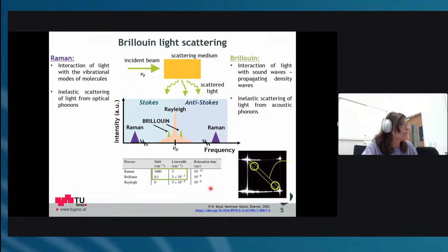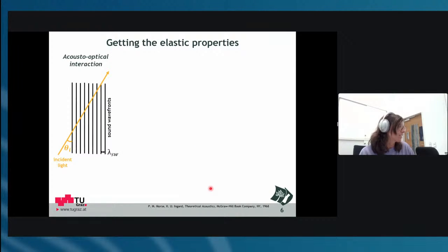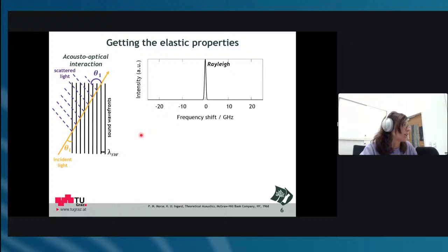And yeah, but now we want to use this method to measure mechanical properties. And how to do that? So we shine the incident light onto a sample in a specific geometry. And in our material, we have sound waves always propagating in all directions, basically. With the way I shine my light in and with the laser wavelength, I can determine the direction of the sound waves that I want to investigate. So the laser light is scattered from these moving sound waves in the material. And this is recorded in the spectrometer, and then I get a spectrum. You have a very huge Rayleigh peak, which is at 0 frequency shift.